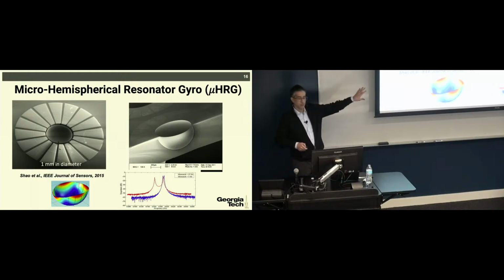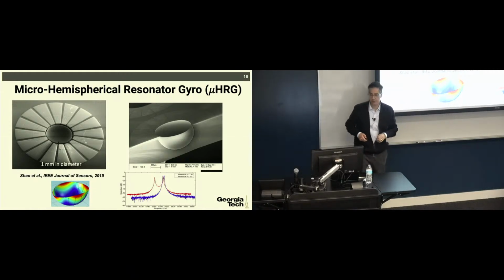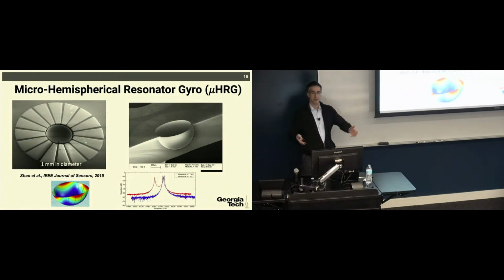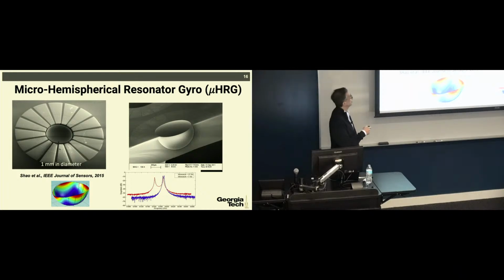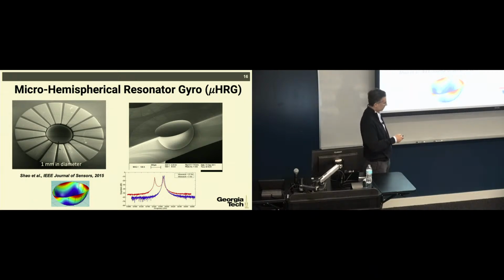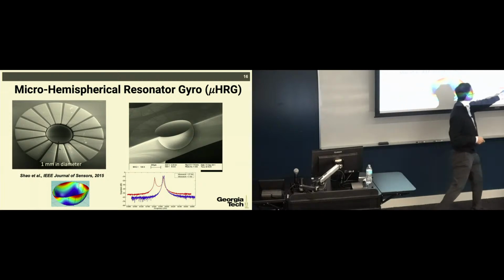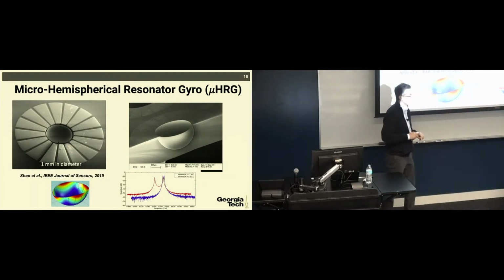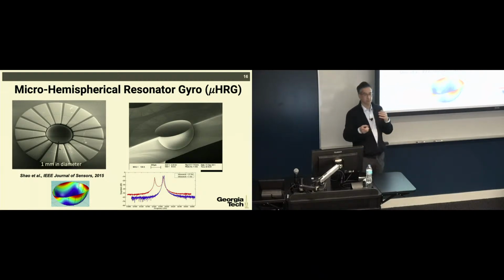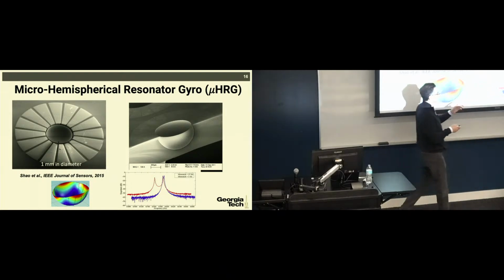Nonetheless, we set out to actually make a micro hemispherical resonator gyro out of a technology that used a hemispherical resonator. And what we wanted to do was to integrate capacitive transducers around the structure. This was the work of Peng Xiao, a brilliant student who was able to get this thing to work. So this is the cross-section of this embedded shell resonator inside the body of silicon. And what you can see here is that, as born, without doing any matching or tuning of the modes, the two frequencies of the gyroscopic modes are slightly separated. They are supposed to be on top of each other, but because of process variations, they are slightly split from each other. Then we mode matched the device using electrostatic forces, and that is shown by the blue curve.